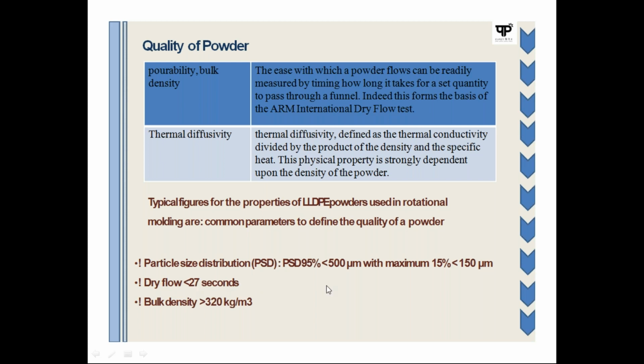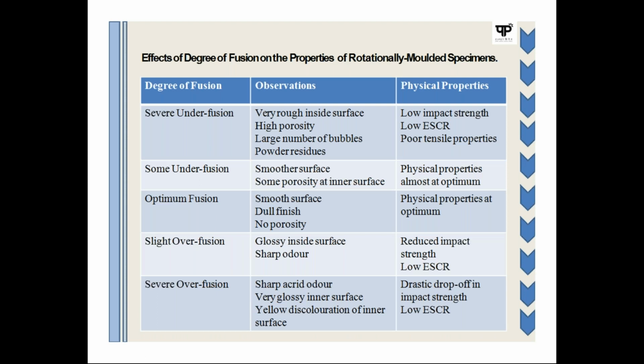Another one, you can see the effect of the degree of fusion on the properties of rotational molding. As I said, if you have a severe under fusion, if the material is not fused properly, then the surface is going to be very rough, high porosity is going to be attained, more bubble formation is going to take place, and powder residues are lying there in the product once you are ejecting the product out, right?